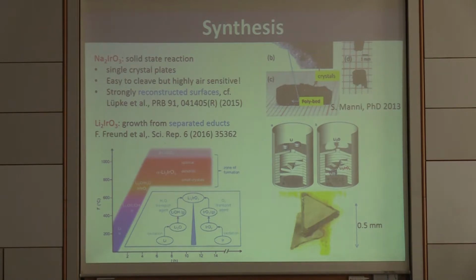So we just give hot air, and actually the air shouldn't be too dry because we also need the water content in the air. Then we get the formation of oxides and hydroxides. The water acts as a transport agent for the lithium hydroxide, and the oxygen in the air acts as a transport agent for the iridium oxides. And then on the spikes, which we put later in the crucible, we get a nice growth of plate-like single crystals, as shown here.